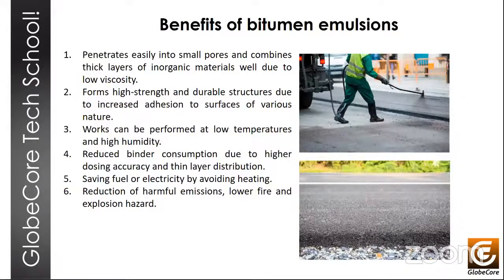So there are obvious benefits to this. One is that the viscosity of bitumen emulsions at room temperature is several orders of magnitude lower than that of actual bitumen, straight bitumen. So low viscosity ensures easy permeation of bituminous material into even the smallest pores, and ensures its alignment even in thick layers of inorganic material.